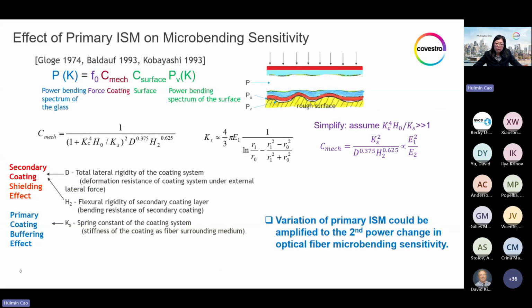One direct consequence of this sharp increase of modulus versus conversion at the last stage of cure is the fiber microbending performance, which is critical for overall fiber optical performance. And this will get worse with a rising primary modulus on fiber. From the classic model of dual layer coating mechanical microbending sensitivity, expressing the primary coating's buffering effect and the secondary coating's shielding effect, the factor Cmech, meaning the coating mechanical property factor, is roughly proportional to the square of the primary coating modulus on fiber. When you correlate a coating property to fiber, you should use the property on fiber instead of on film, which could be very different. So even a very small increase of primary in situ modulus could amplify fast into a higher microbending sensitivity of the coated fiber.